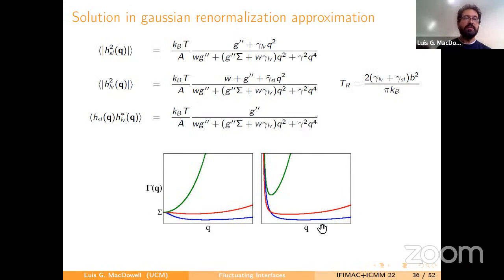Okay, and this looks very complicated, but surprisingly, it can be solved exactly under a Gaussian renormalization. And the result of that is the spectrum of surface fluctuations. But we have two surfaces, so we have results for the two surfaces. Fluctuations of the solid-liquid surface, fluctuations of the liquid-vapor surface, and actually coupled fluctuations, solid-liquid-vapor. And you also find that this system has a roughening temperature. Okay, and it's very difficult to interpret these results right away, but it's very easy to do it graphically.